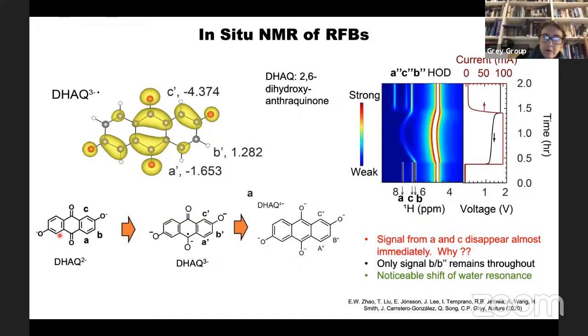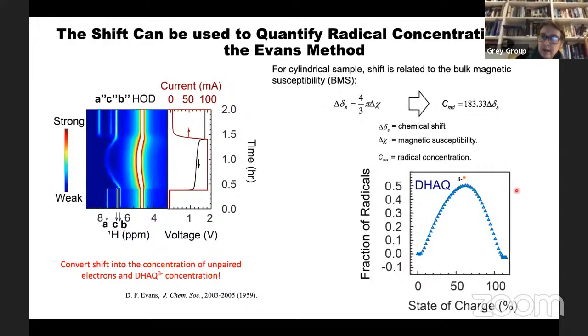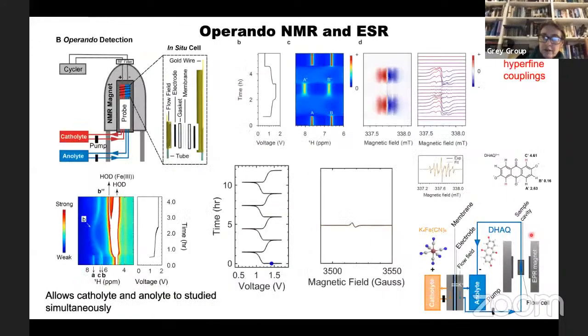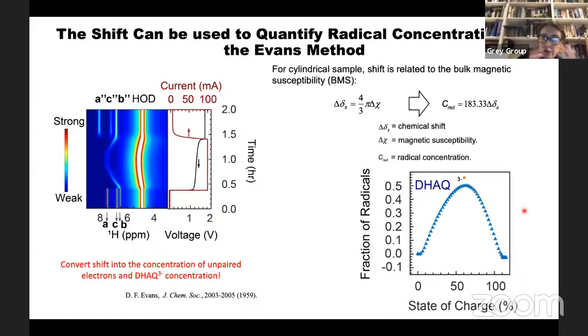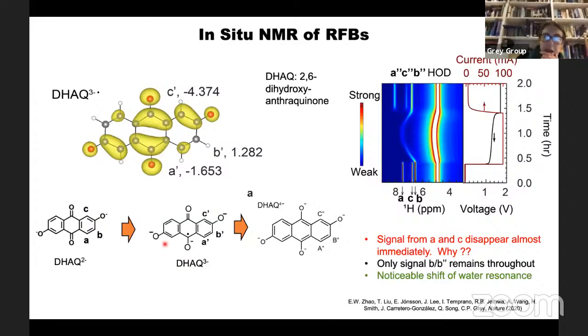You notice that it's not 100%. So we're not going via a one-electron process from this to this to this. We're reaching a 50% maximum, which I'm showing here, and then it's decreasing. That's because you've got, let me see if I've lost the slide on this, multiple competing processes, where the difference between the potentials of this couple and this couple is very small.